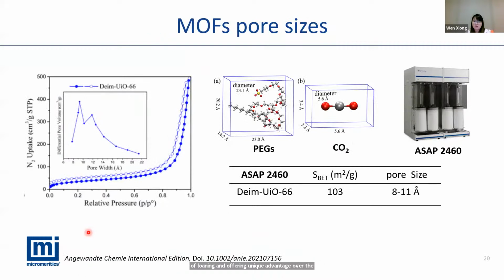Now let's see some real examples to check how the pore size or the pore structure affects the adsorbent or the membrane performance. Pore size distribution is a key parameter for MOFs, especially for gas adsorption and gas separation applications. In this case, the customer was using our ASAP 2460 and collected a good isotherm of the materials. The data reduction shows the pore size, calculated using the HK model, is about 8 to 11 angstrom.